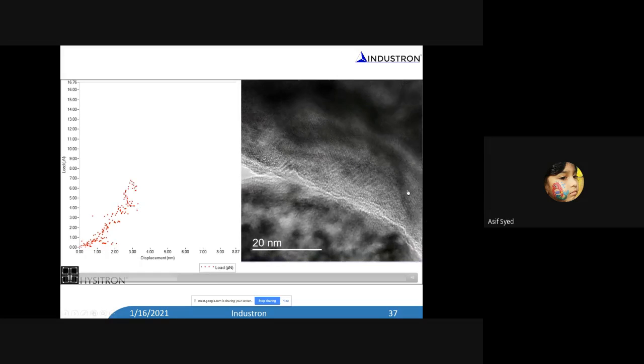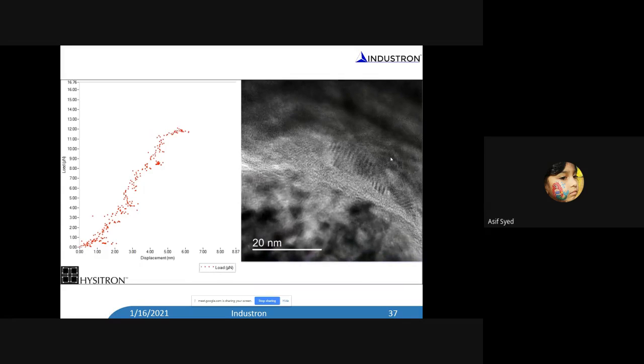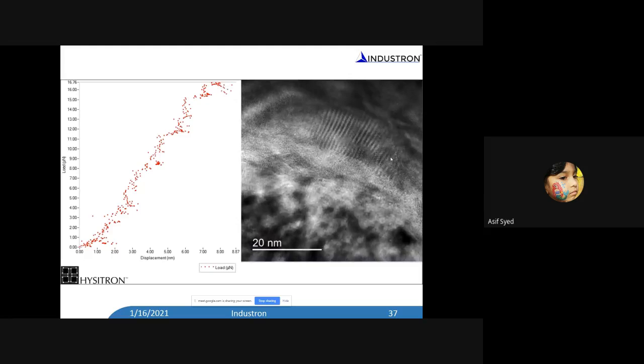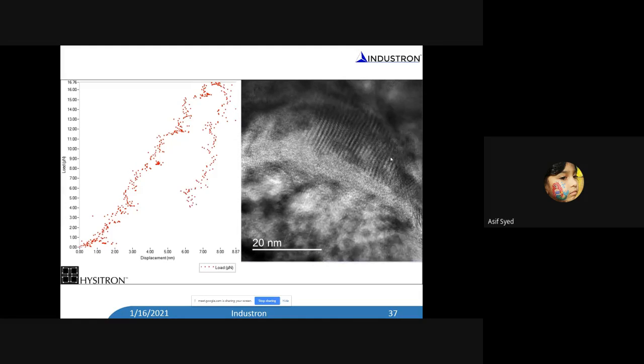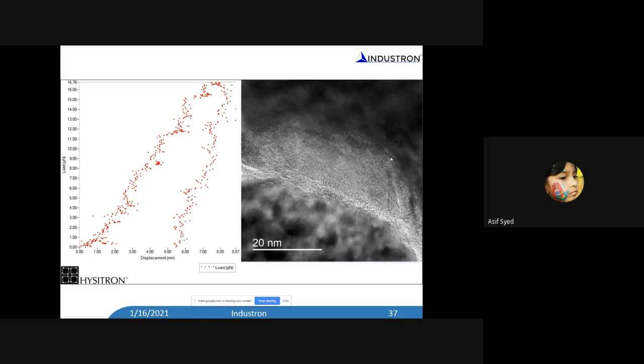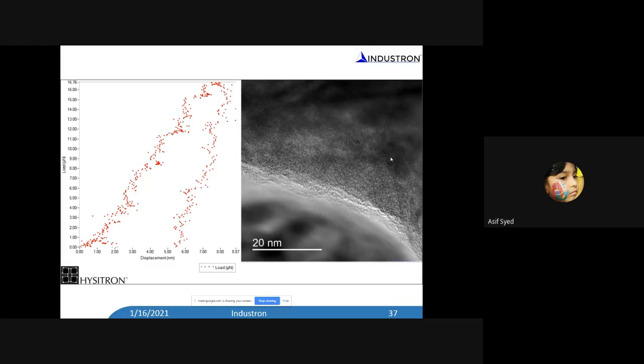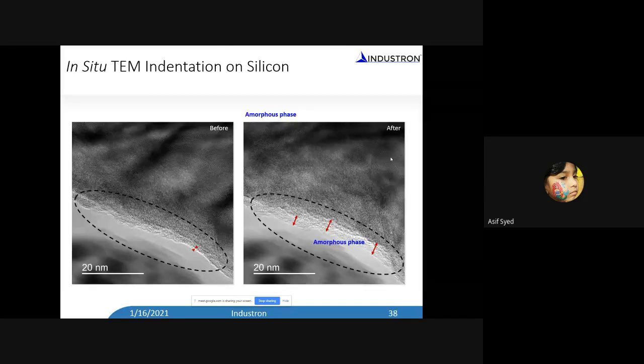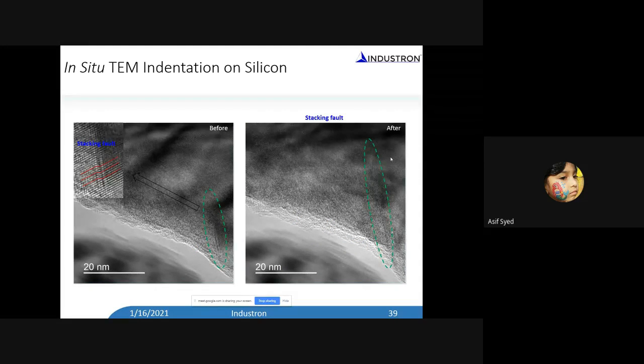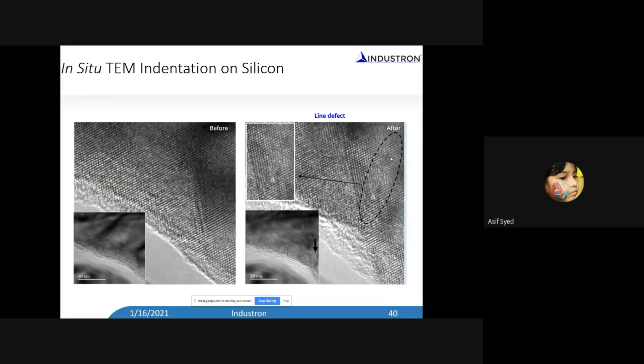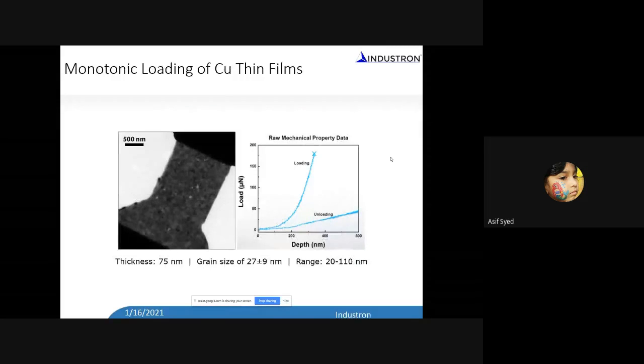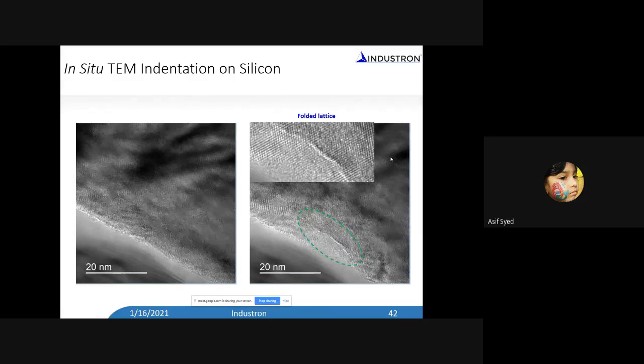For example, you can see the stacking fault here, and I will go through this slide. All this perturbation that you see in the load-displacement curve is not noise. It means something. Defects are created, you create vacancies, stacking faults and other things as you do the deformation. This is an atomic resolution image, and we can get the load-displacement response. When you bring the tip and make contact, initially you see an amorphous phase. We never expected an amorphous phase first. Then you can see the stacking fault, and after the indent, how the stacking fault grows, line defects, lattice rotation. So you can see atomic scale defects, and I can correlate that with the load-displacement curve. We need to develop much more understanding, but we have the tools which allow us to go to atomic scale and make observations and measurements.